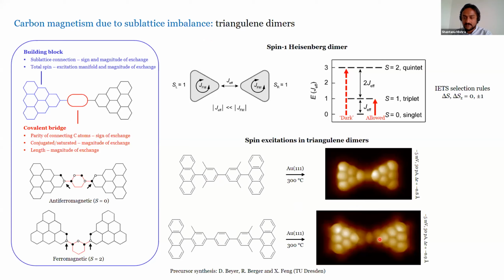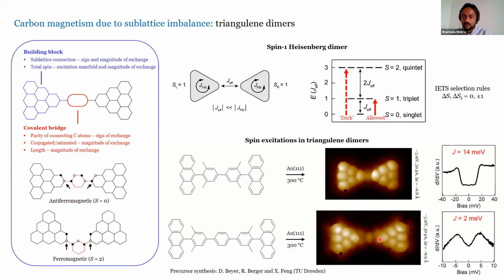I don't show that here for brevity, but the most important thing is that now if we go near the Fermi level, you actually see these inelastic steps, and the energy of this inelastic step drastically changes when you increase the spatial separation from being directly connected to separated by a phenylene spacer. So what we believe is that these are actually spin excitations. In this case, it's 14 millieV, and it drops substantially, by more than 85%, to about 2 millieV when you separate these two, since you're having obviously less overlap of the wave functions of these two magnetic units.